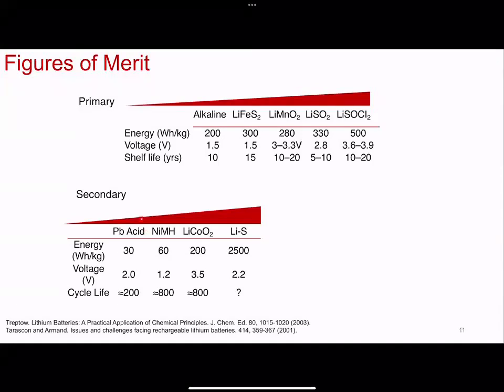So lead acid battery, dominant in vehicles for a while. So if you want to be able to unlock your car or things like that, or rolling up your window, or rolling down your window, right? That uses a lead acid battery. So here the energy density, the gravimetric energy, so that's normalized by mass, is 30, compared to nickel metal hydride, so that's 60. So already we've increased 2x in energy. And then you jump all the way to lithium cobalt oxide, because lithium is so much lighter, you jump up to about 200. I mean, this is a sort of floating number, right? The technology is developing by the day. So this number is increasing by the day, in terms of what we can engineer this material to do.